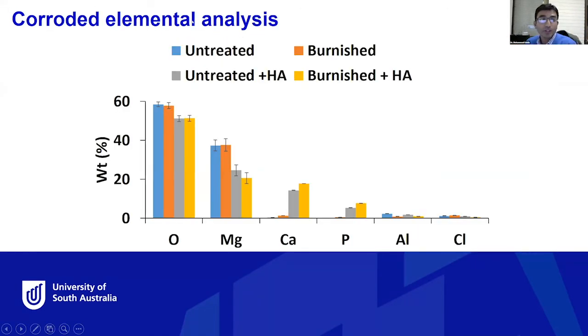And finally, I have got a corroded elemental analysis. This is just to show you the retention of the elements as the surface is being degraded. We can see that in the case of the burnish plus HA coated surface, the calcium and phosphate increase, which is quite natural because it has an HA coating on top. But we can see a lower amount of magnesium in the case of the burnish plus HA coating. That means less degradation, or fewer corroded products being generated, in the case of the hybrid treated surface.